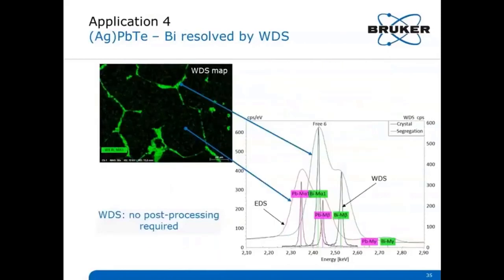To test for the bismuth indication by EDS, we used WDS and gained overwhelming evidence. So we set the system to the bismuth line, mapped for bismuth, and found bismuth everywhere in the segregation areas surrounding the crystals. And yeah, you can nicely see this here in the WDS map.